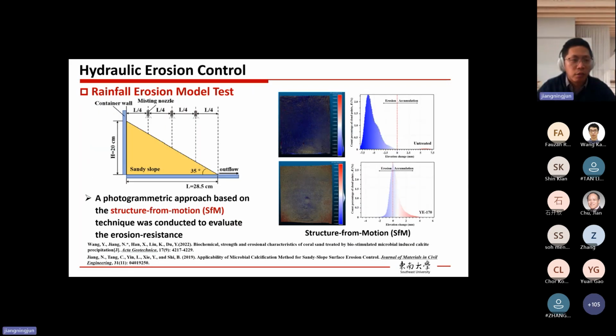With the same apparatus, we also simulated rainfall erosion by using misting nozzles on top, so we can simulate rainfall at different magnitudes. In this test, we used a photogrammetric approach, structure from motion, to quantify the erosion. From the graph on the right-hand side, the blue part shows the erosion. If elevation change 0 means no erosion, then the minus means erosion. For the untreated case, we can see a lot of erosion, mostly uniformly distributed in the center part.